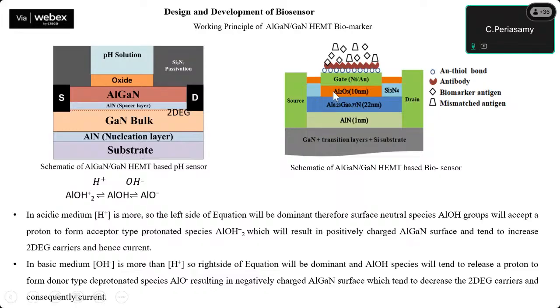So here one can choose Al2O3 or SiO2, which will react with the pH sample, because in a pH sample there are acidic and base components. That acid and base will react with the hydroxide group of either the SiO2 or Al2O3 layer, and it will change the surface potential of this HEMT transistor, which will affect the output characteristics, particularly the drain current across this device. So this is the working principle of the HEMT structure for pH sensing application.